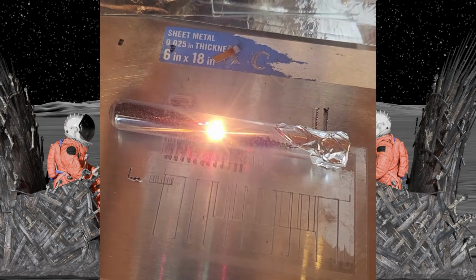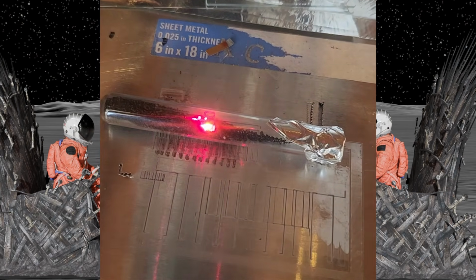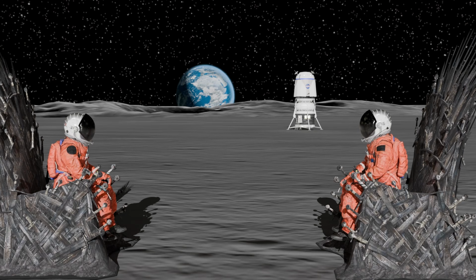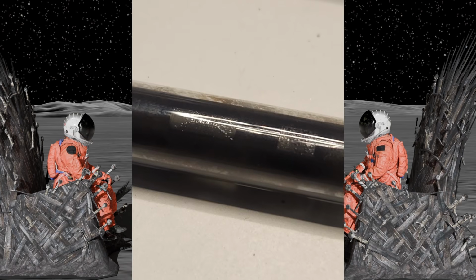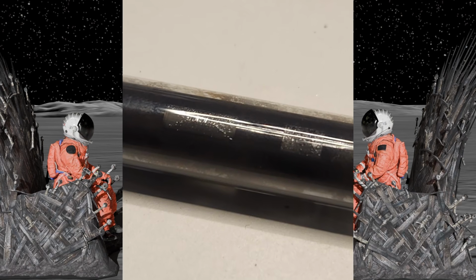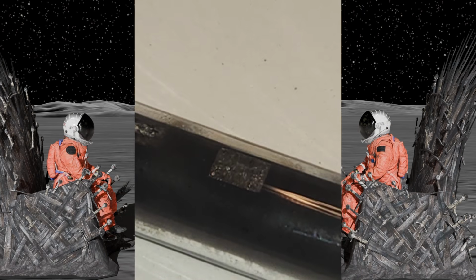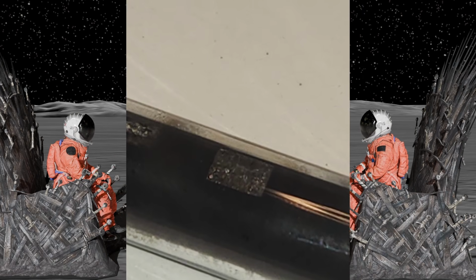So we did everything from all of the simulant samples to the individual metal oxides. What we did find is that some of these metals will absolutely reduce by laser under vacuum. They don't have enough time to bond back with the oxygen, and they deposit on a cooler surface. We've had really good success with iron. We've had some success with magnesium, aluminum, and we're currently working on calcium.